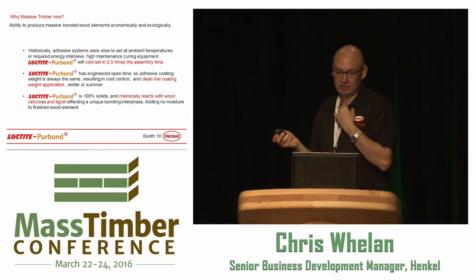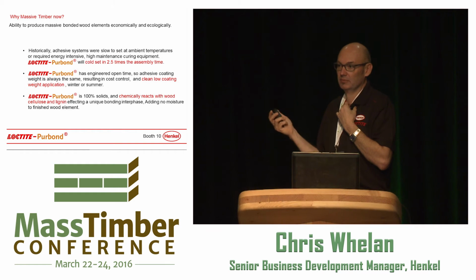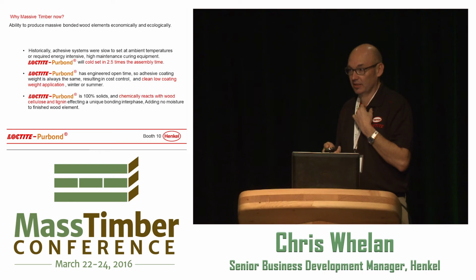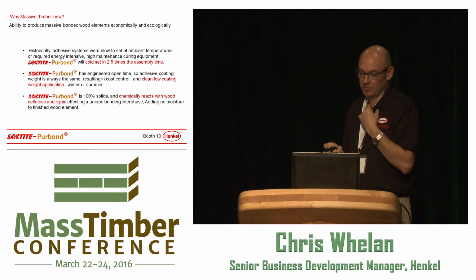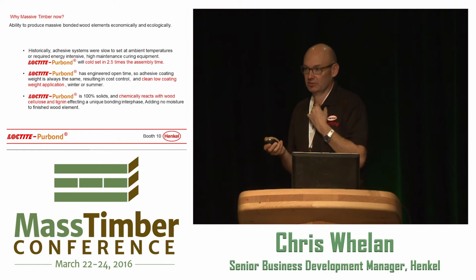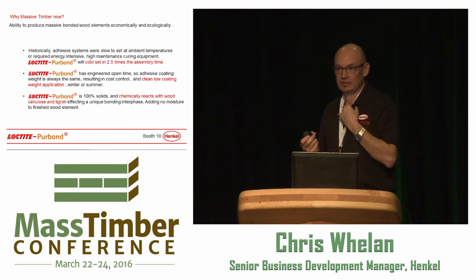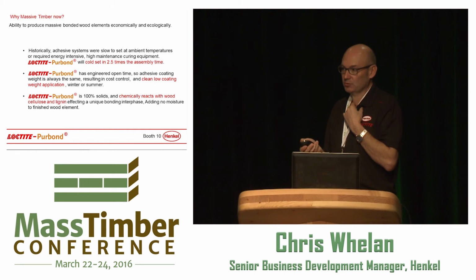We're 100% solids. There's no solvents. We don't have any formaldehydes. We have very little waste. We don't have water waste. We don't have wash water. We don't have issues like that, which helps us from an ecological standpoint. It chemically reacts with the wood, cellulose and lignin. So it's not just creating an interface bond, it's creating an interphase bond. So it's actually reacting with the wood itself to affect this bond. And this is a very important thing to consider in these new mass timber structures that we're doing today.